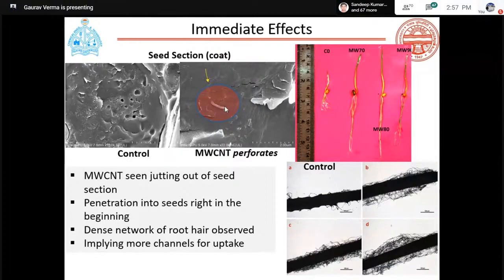And this we were able to conduct from our material science background and ensure that yes, the carbon nanotubes do enter the seed coat, and we saw one of the carbon nanotubes jutting out when we undertook a scanning electron microscopy of these samples. And when we looked into control, because when you're dealing with biological samples, you can always be sure that these fiber-like features are very common. So it's very difficult to distinguish between a carbon nanotube and any normal natural feature you would see in a seed coat.